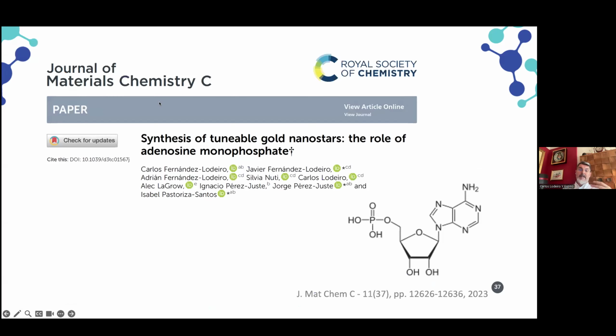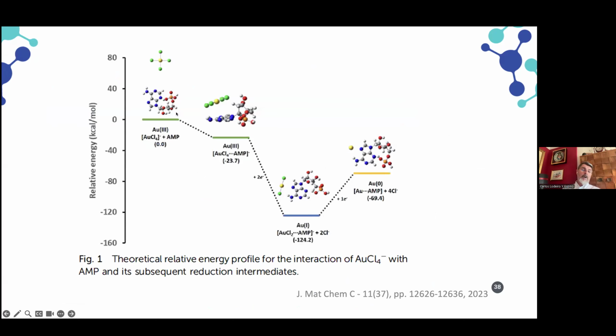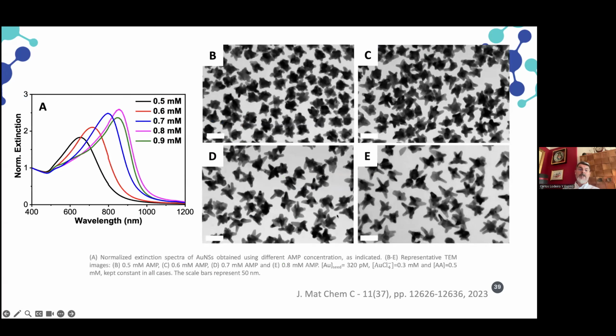These nanoparticles can also be stabilized with adenosine monophosphate, and this paper reported the results with the stabilization by adenosine monophosphate on the surface of the nanoparticles. We started to form an inorganic complex. The inorganic complex formed by gold evolved with the coordination of the AMP, and after the coordination with the AMP, gold 3 is reduced to gold 1, and then gold 1 is reduced again to gold 0, producing the nucleation of the nanoparticle. So here I show you images in which, in this case, we can also maintain a very stable suspension with very long tips of the nanoparticles, maintaining the plasmonic band close to the infrared, where we can achieve 900 nanometers.